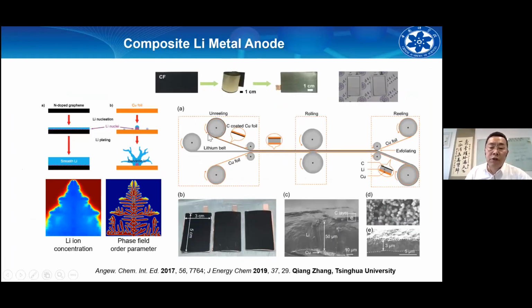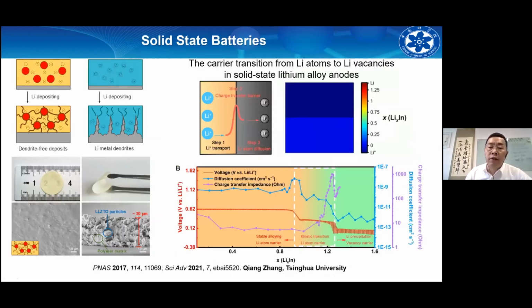And another research group from Tsinghua University also used something similar to pre-lithiation, just printing carbon fluoride powder slurry on the surface of lithium to get a mixed ionic conductor surface coating, just to counter lithium plating formation. And they also checked the interface of the solid-state battery. I will skip these details.